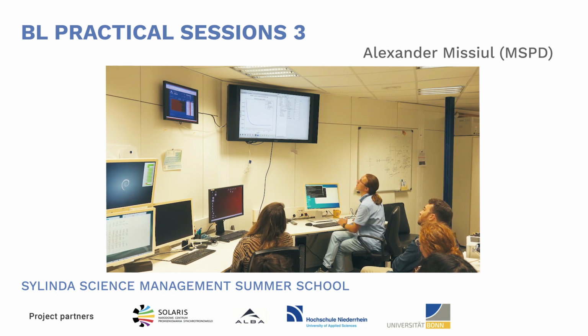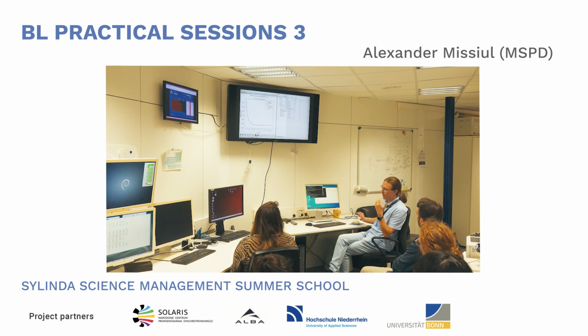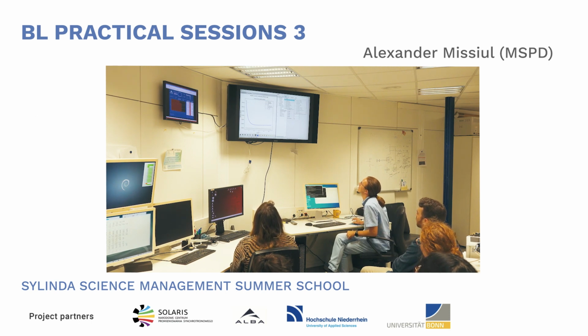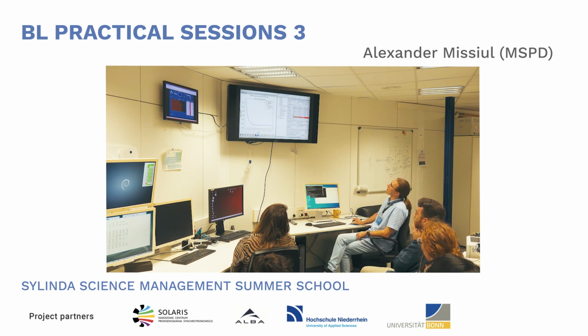And of course, because it is refinement, which means that we try to adjust the model, we have to import the starting model, which will be essentially the CIF file that I downloaded from the crystal structure database. So we will start with just one, see how it works with the copper iron oxide. You see, we can refine many parameters. We can refine the lattice parameters here. We can refine the phase fraction. We can refine size. We can refine strain. And we can refine all the atomic parameters like coordinates, occupancy, or thermal oscillation parameters.